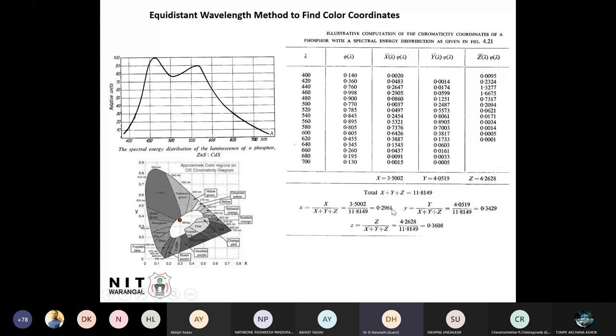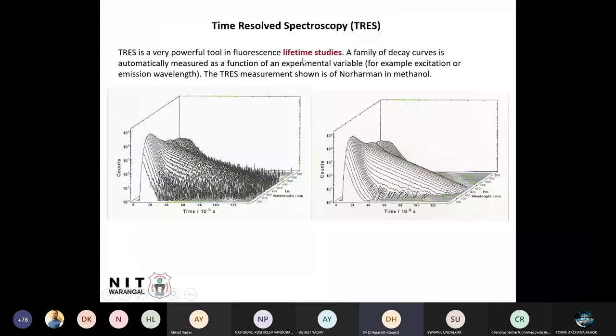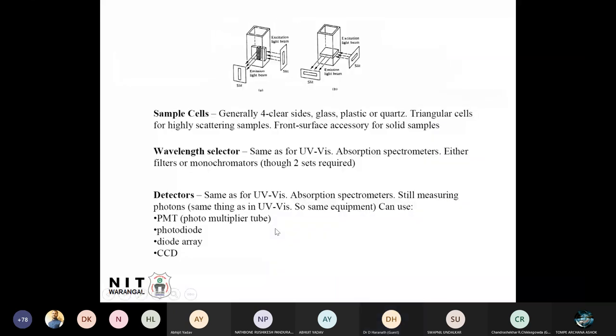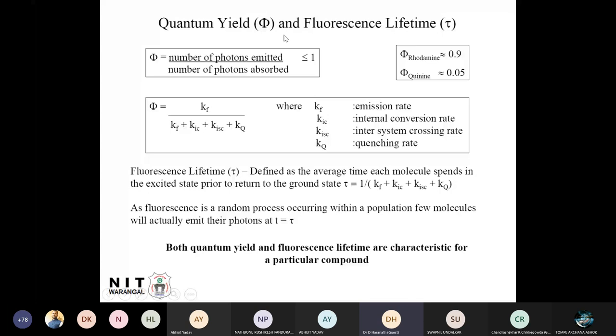Time-resolved spectroscopy, as I told you, gives the lifetime measurement: how much time the electron rests in the higher energy state. You can determine it for liquids also. The other way is quantum yield or quantum efficiency. You have to take some known material with a quantum efficiency of 0.9, which is very good; 0.9 is 90%. You measure the quantum efficiency using this one, then replace it with your phosphor, and correlate. Quantum efficiency is the number of photons emitted to the number of photons absorbed. So how do you count the number of photons? There will be a photon counting system attached to the spectrometer.